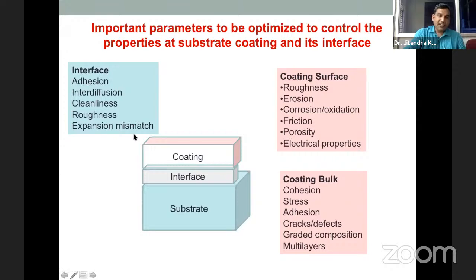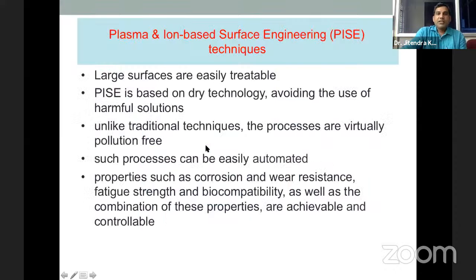And roughness, cleanliness, expansion mismatch. So these are the various parameters according to the different regimes: substrate, interface, and coating regimes. So this is the first method, which was developed around 1960, the plasma and ion-based surface engineering technique. And here a large surface can be easily treated by this plasma ion based technique. This type of technique you can easily automate by some other means, and the coating generated by these techniques is used for corrosion and wear resistance coating, and also you can improve the fatigue strength and biocompatibility of the surface.